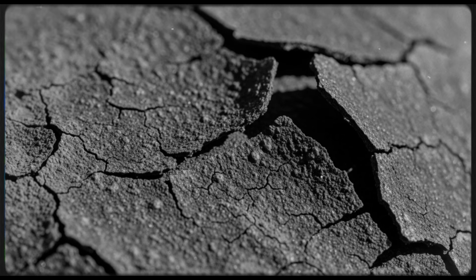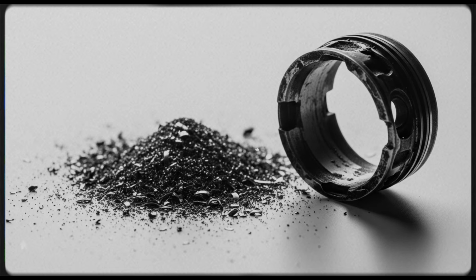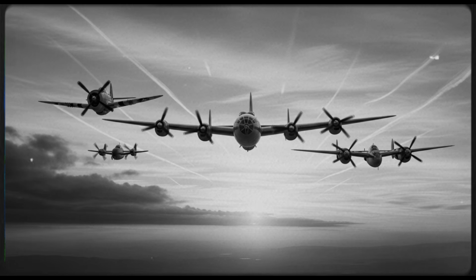So when military officials arrived at Hastings in 1940 with a demand for rings that could endure 200 hours, not a mere 40, the engineers felt they were being tasked with rewriting the rules of materials science. Cast iron simply couldn't take the punishment. The material was too fragile. Under extreme heat, it lost its essential springiness and failed to seal. The carbon within the iron would oxidize, causing the ring to literally wear itself into dust. By the 50-hour mark, it was just metal scraping against metal. By hour 80, it was useless debris.